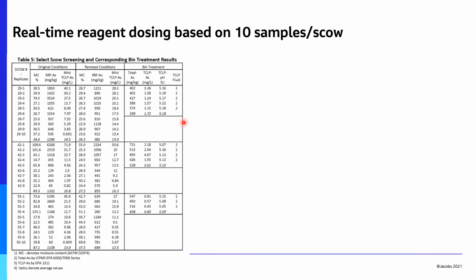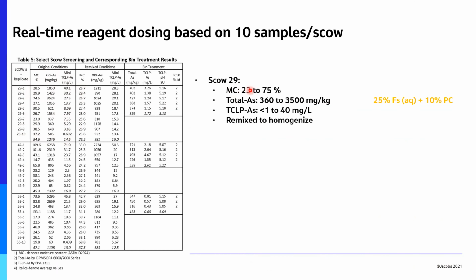As you take a look at this first one, we had moisture content from 23 to 75. Our totals were about 360 to 3,500. Our T-clip max on this one ended up being about 40, but you have a huge spread in your T-clips. So we were concerned that with such variation, what we really needed to do was even things out. So we sent this to be rehomogenized.